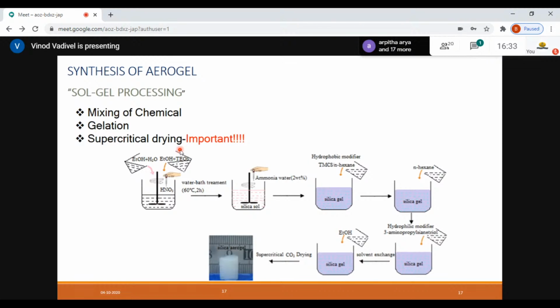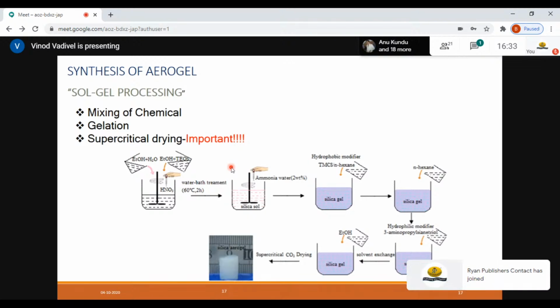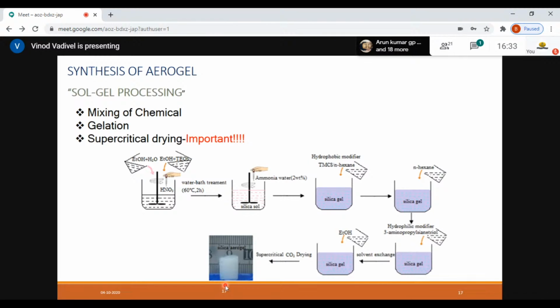Generally, this is the main part for the aerogel form, because if you dry it in an oven, it's not going to work. It's just going to have your materials dried. That's it. You will not find your aerogels. Supercritical drying takes a lot of time to explain, but it's carbon dioxide supercritical drying, where you supply liquid carbon dioxide at a particular pressure to reach supercritical conditions. It's around 73 bar. When it reaches that, it becomes supercritical, and there is a solvent exchange happening. After that, the material becomes more fluffy and more flexible.